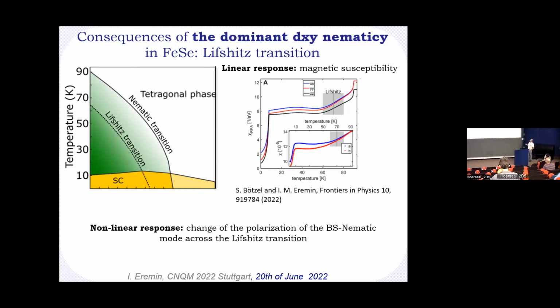Maybe one of the most recent is that if you look into the behavior of the uniform susceptibility below the nematic transition, you suddenly see a very non-monotonic piece, which is exactly coinciding with the onset of the Lifshitz transition. This is about the linear response, but what is also important is what you find in this regime, where your Bardasis-Schrieffer mode is essentially a nematic mode, which by virtue of the coupling becomes a nematic mode. You can clearly see a change of the polarization across this transition, which can be used as a probe of whether there is a dominant dxy nematicity.